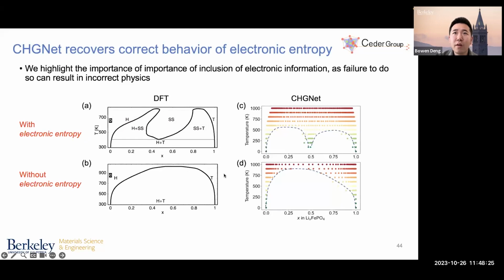So we use the fine-tuned CHGNet for both energy and electronic state calculation in combination with the cluster expansion to run the Monte Carlo simulation to simulate this temperature-dependent phase diagram. The result is shown in figures C and D on the right. So we qualitatively recover the correct behavior of electronic entropy induced eutectoid transition, which shows that the CHGNet captures the correct distribution of electrons and holes.